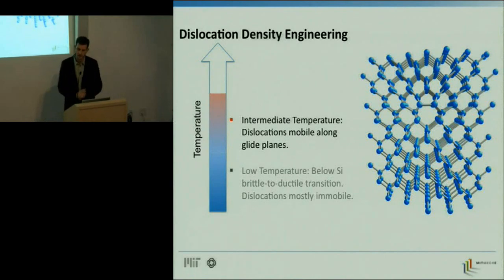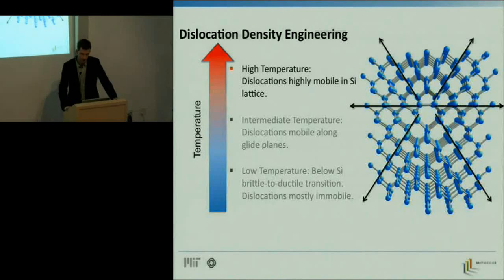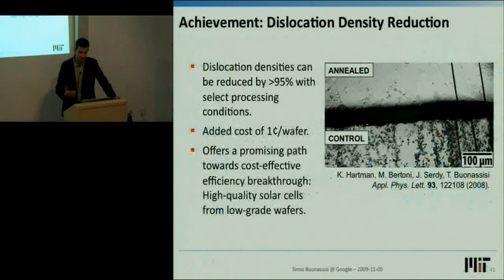This for silicon occurs around 500 degrees Celsius, but because of the unique crystal structure, you're still limited in how mobile these dislocations are. You really need to go above 1,000 degrees C before you start getting dislocations moving freely throughout the lattice. And note that silicon melts at around 1,400 degrees Celsius. So these are very high temperatures. And this little dislocation core structure, denoted here with this defect, is free to move around the lattice. So with this knowledge in our minds, we sought out some ceramic annealing furnaces and developed a process at MIT where we can eliminate the dislocations inside of these multicrystalline silicon materials.